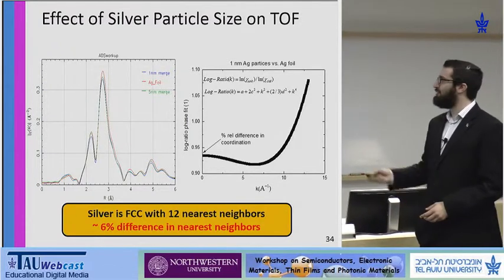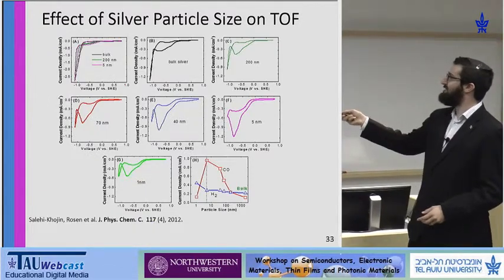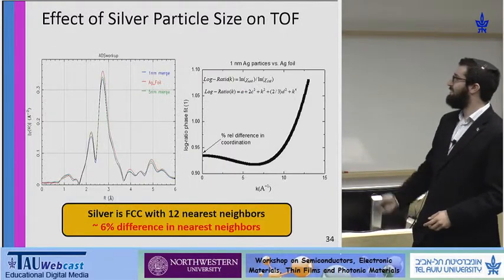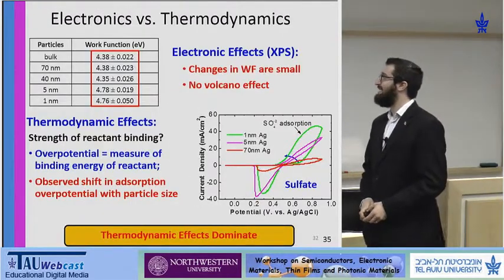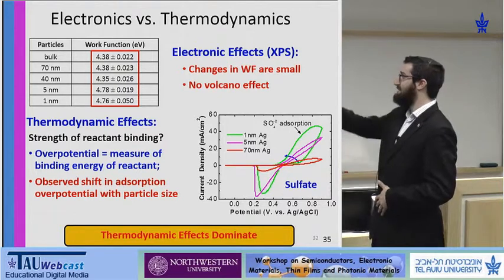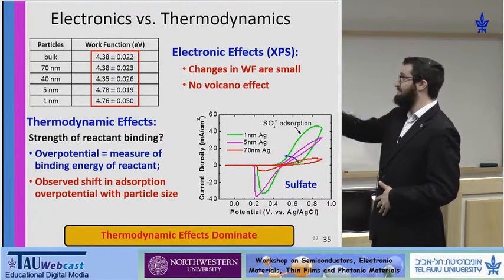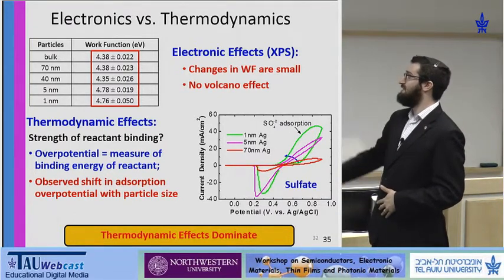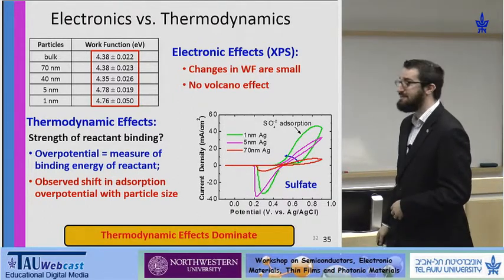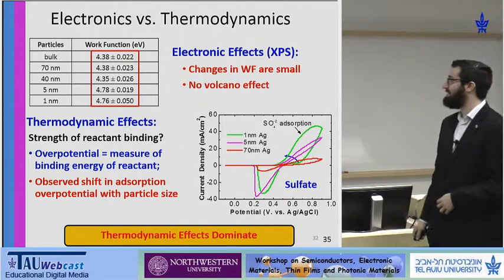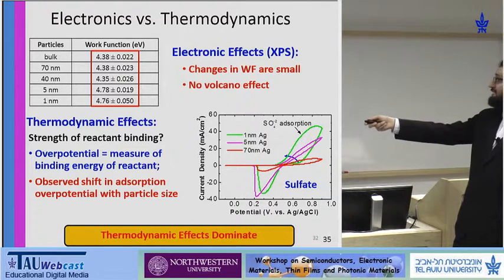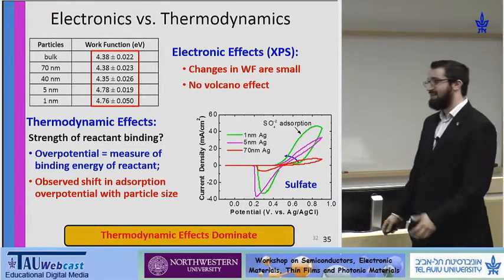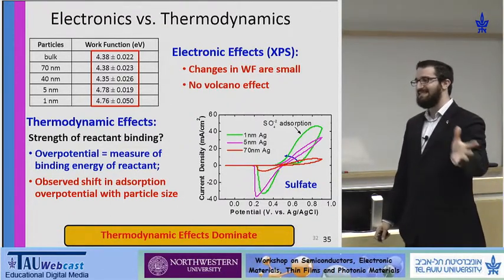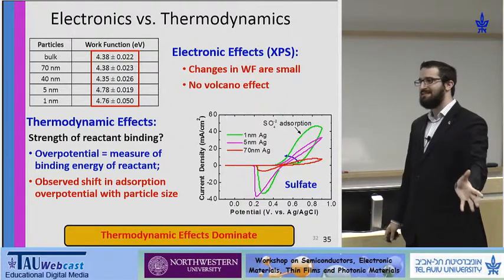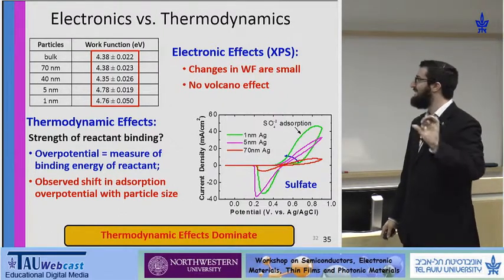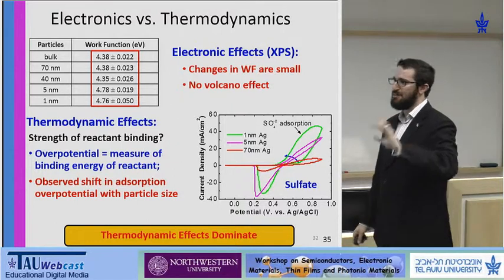So we can't attribute what is effectively a 10-fold change in activity to less than an atom. But what we can look at is electronic and thermodynamic effects. The work function of different sized particles shows not a significant difference, certainly not a volcano activity like we see in the carbon dioxide conversion. But what we do see is the thermodynamic effect that these different sites, these different crystallographic orientations based on particle size, have different adsorption energies.